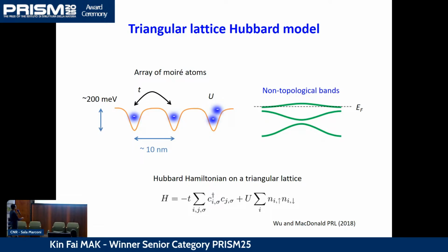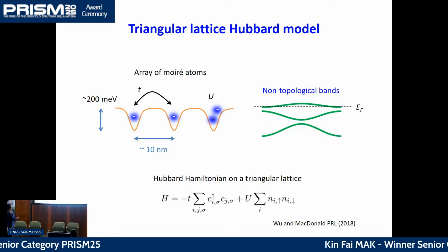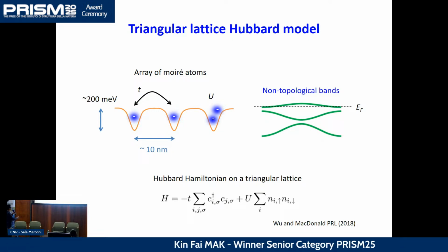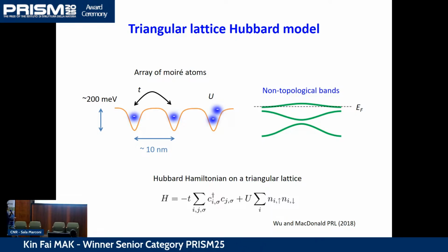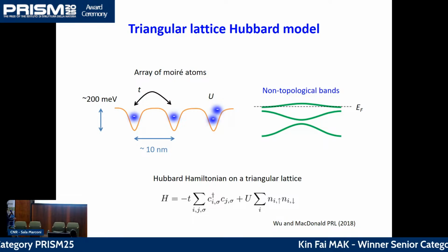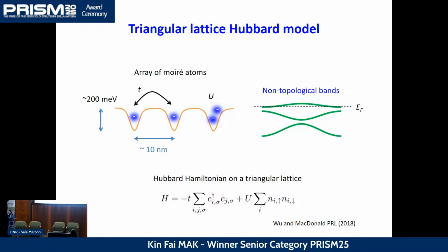So first of all, let me go back to this picture of an array of artificial atoms, where the electrons are trapped, but they can actually still hop around. And the hopping rate is this t, which is the kinetic energy of the electron here. They can hop between neighboring sites, and if you end up with 2 electrons on the same site, they would Coulomb repel each other strongly, right? So that causes a Coulomb repulsion energy of U here.